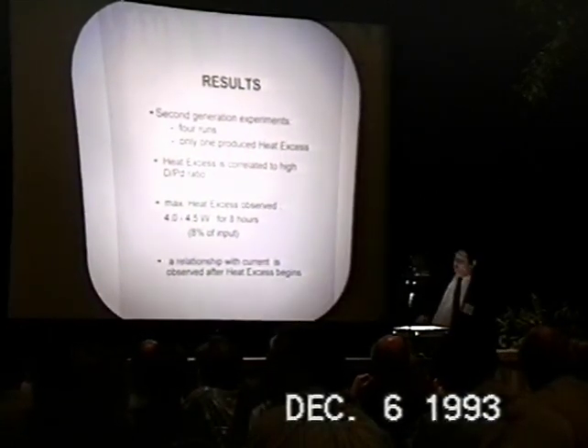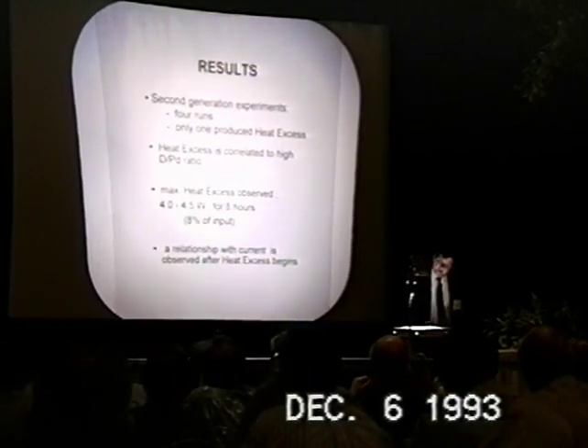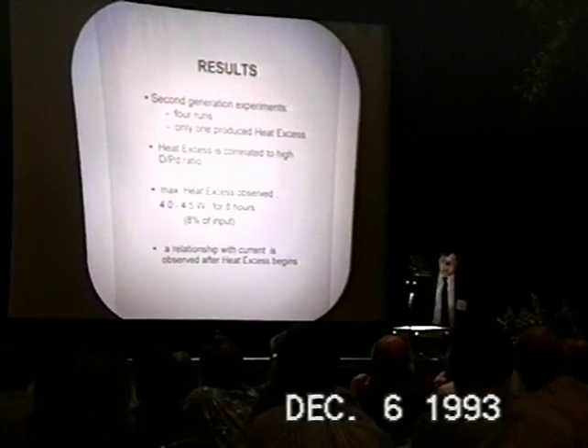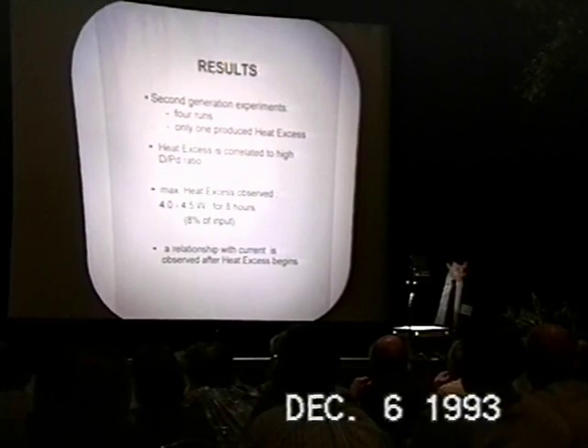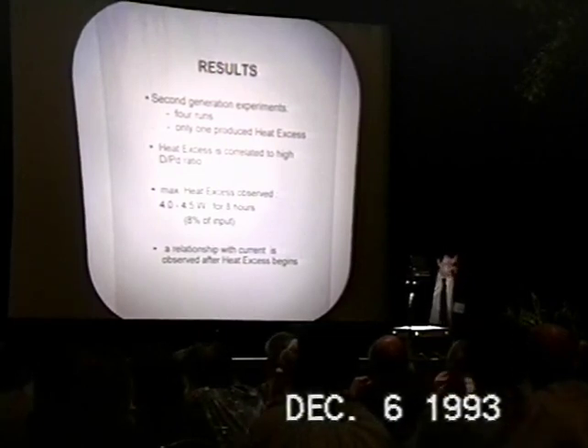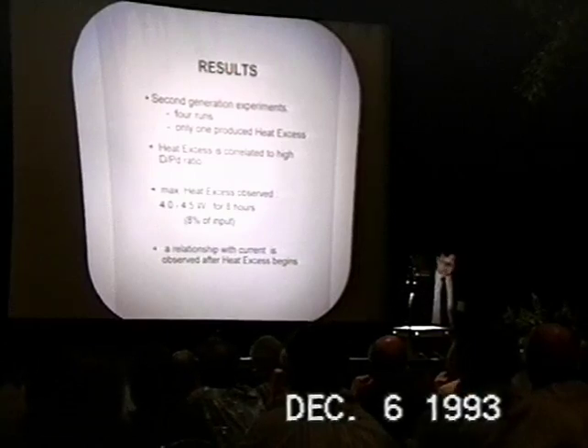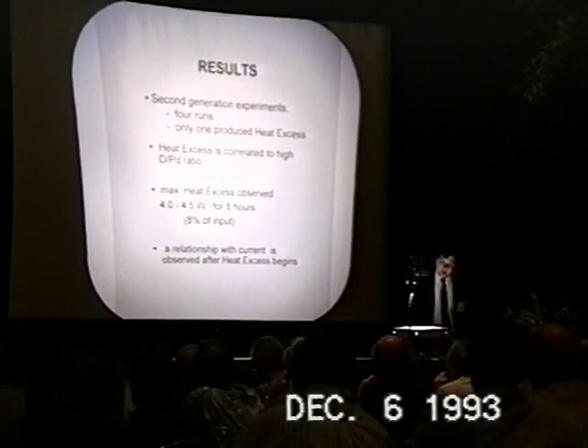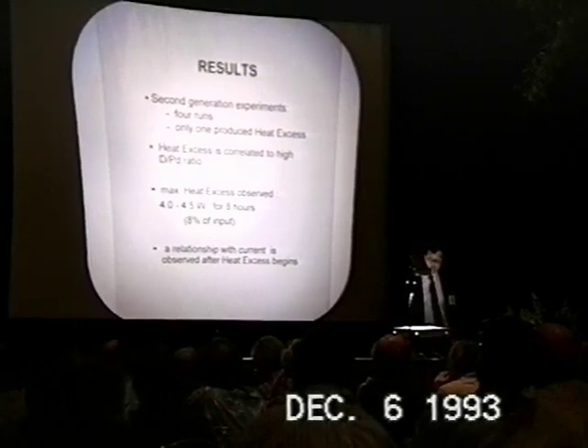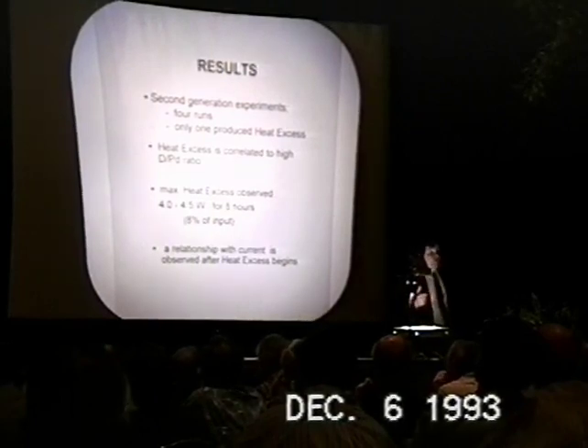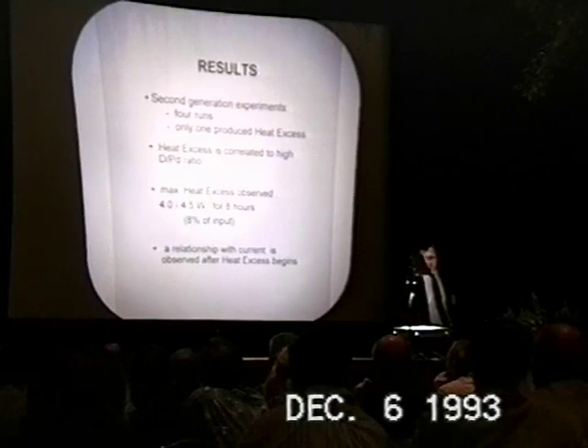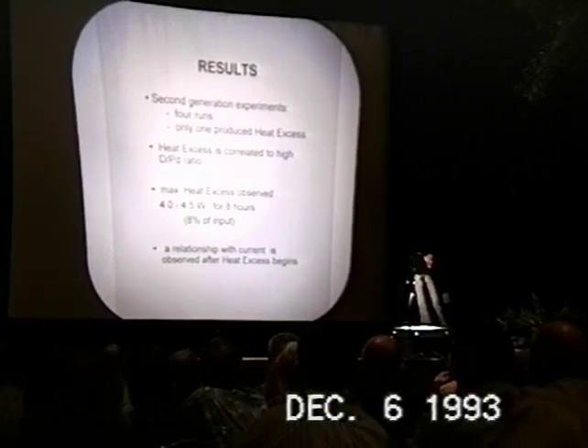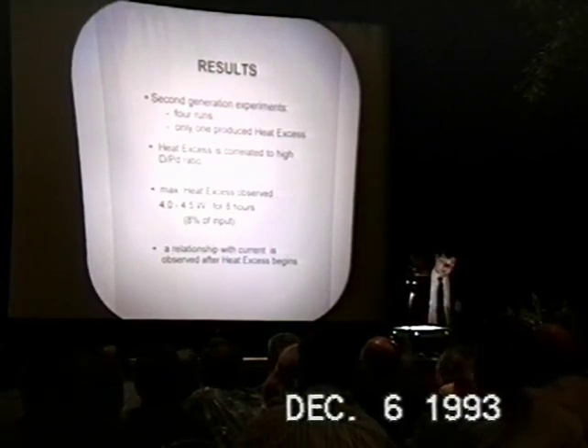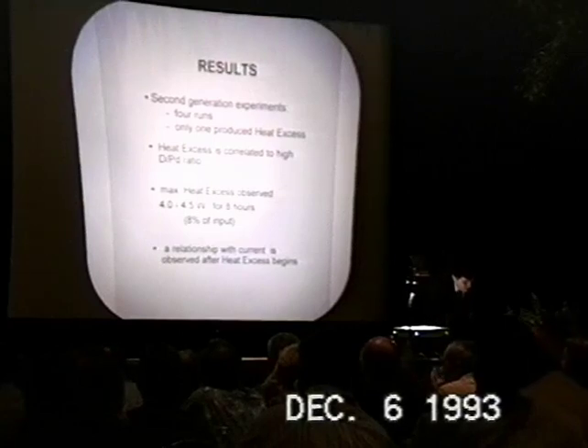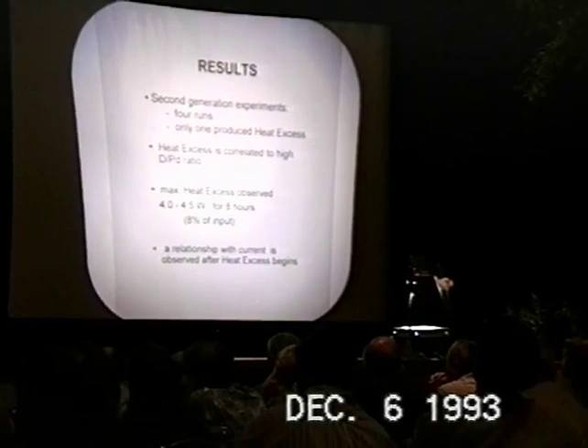Here are the results on the heat effects. These are the so-called experiments of the second generation. We had 4 runs. The 4th one is running now, and I don't know if it's still going on or if it produces heat effects. But up to now, only one produced heat excess. This heat production is surely correlated to the high D/Pd ratio because we measure it. It's about 0.75, 0.8. And we have seen a maximum value between 4 and 4.5 watts.